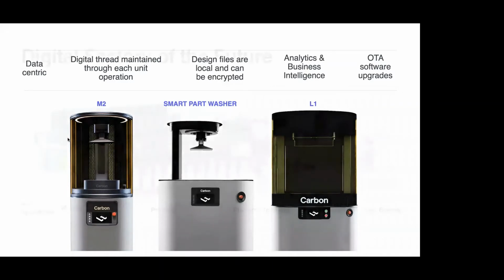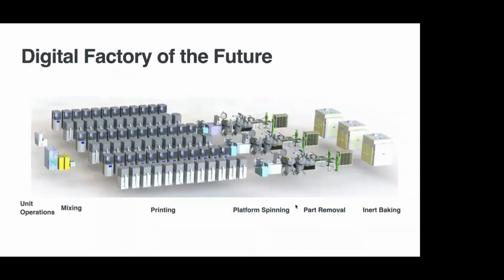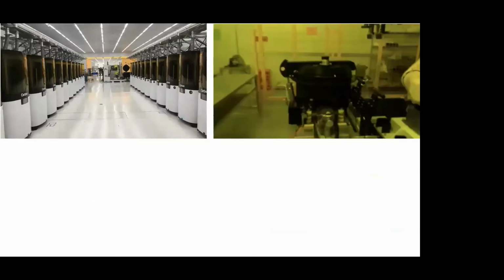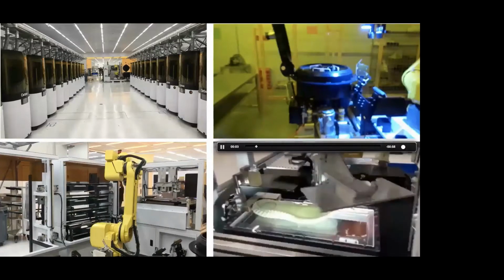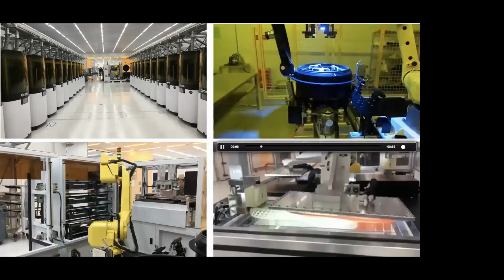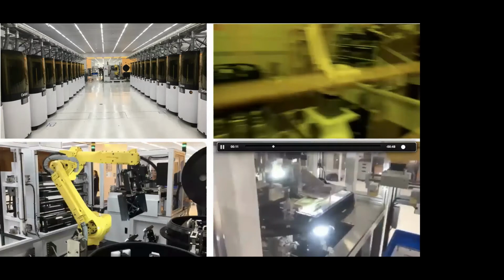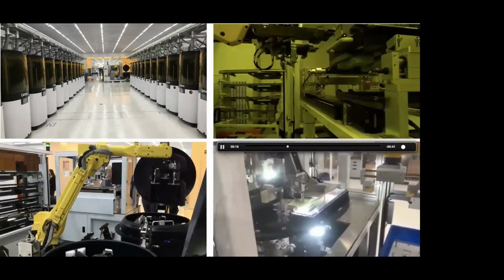And that allows us to begin putting factories together using digital manufacturing. And also, as far as dry back-end processing, thinking about environmental stewardship, instead of using solvents to rinse the parts, we are using centrifugation to spin off excess resin before the second step for polymerization, and collect all the resin and reuse it.